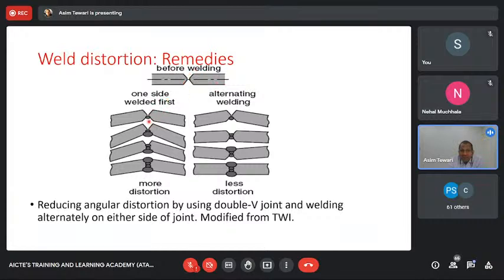So you're adding a material here, then adding material here, then all adding at the one side first, and then adding on the other side. Whereas here you are adding once below, one stop, once below, one stop, and what you realize is it has much less distortions. Now, this is something which you need to realize, that having no distortion doesn't mean that you have no residual stresses. As a matter of fact, you could have more residual stresses, and you are likely to have more residual stresses if you had distortions.